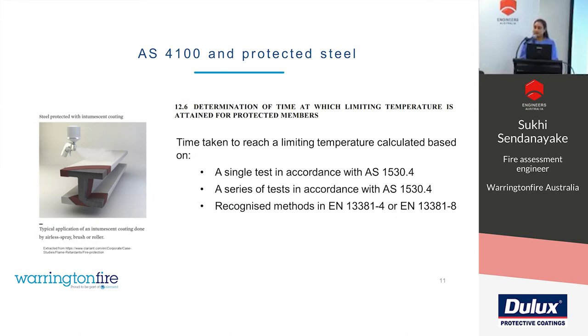So now we can talk about protected members. Clause 12.6 of AS4100 gives us guidance on how to determine the fire resistant performance of protected members. And AS4100 states that the time taken to reach a limiting temperature can be calculated based on either a single test or a series of tests, and all of them have to be conducted in accordance with AS 1530 Part 4. Or, as an alternative approach, Amendment 1 to this standard states that an assessment report can be prepared based on an